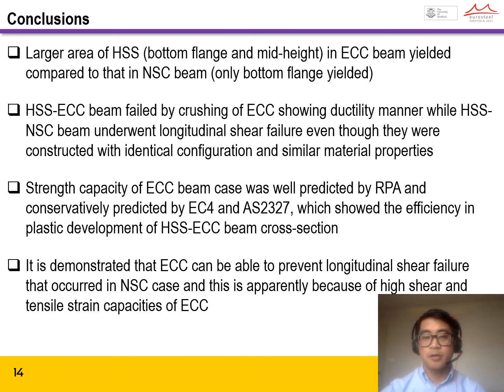The strength capacity of the ECC beam was well predicted by rigid plastic analysis and conservatively predicted by EC4 and AS 2327, which shows the efficiency in plastic development of the high-strength steel ECC beam cross-section. ECC demonstrated that it is able to prevent the longitudinal shear failure that occurs in the NSC case, and this is apparently because of the high shear and tensile strain capacity of ECC.